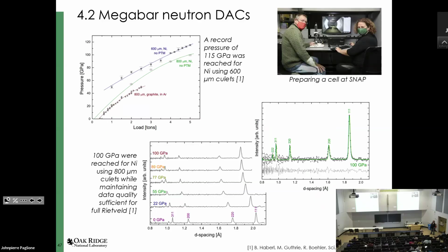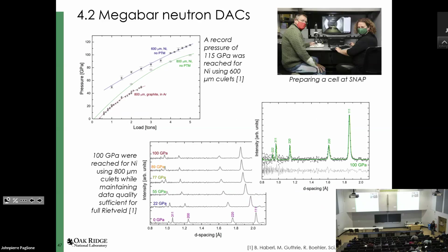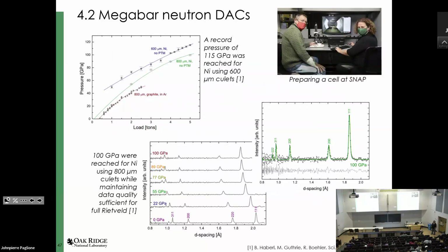Here I just want to show briefly the data we get at 100 GPa. We are cheating a little, because we are using nickel, which scatters extremely well. But these were only 2-hour runs, so it's not like we were counting for massively long times. And Malcolm Guthrie invested a lot of time in analyzing and refining the data. At 100 GPa, you can still do a full quantitative Rietveld refinement, because it's not sufficient to just have a cell that gets you to that pressure. You also need to be able to analyze the data so you actually get out the crystallographic information you want.